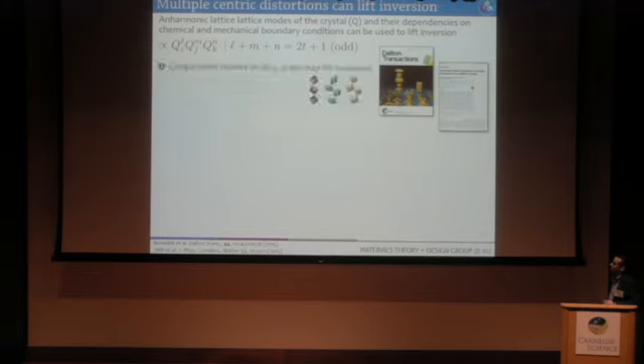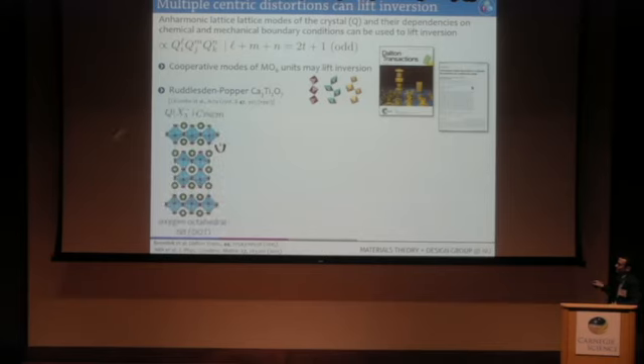And so these modes can typically be rotations of octahedra, and that's the one I'm going to give you an example of on this slide, or they can be other distortions to the octahedra. They can be first-order Jahn-Teller distortions, things that change the shape of the octahedral unit, or they can be orbital or charge ordering types of distortions, which also change the shape of the octahedra. And so these modes can be any one of these types of distortions I'm depicting for these polyhedral units here. And this was really articulated in a nice series of papers on this compound calcium titanate, this 327 phase, the n=2 member of the Ruddlesden-Popper family. And it's shown in this diagram here.